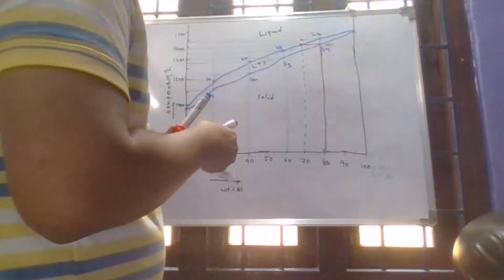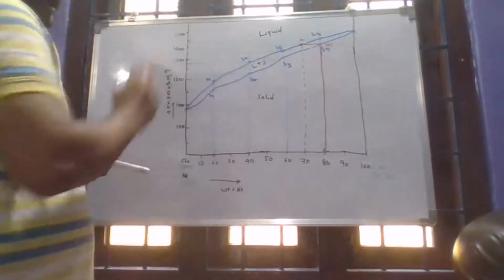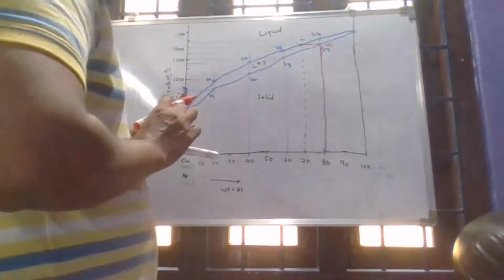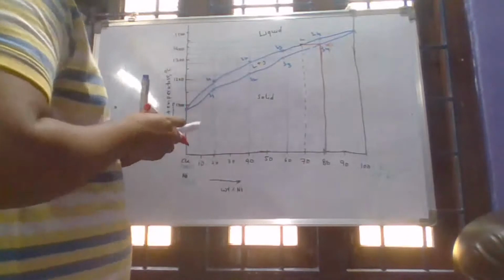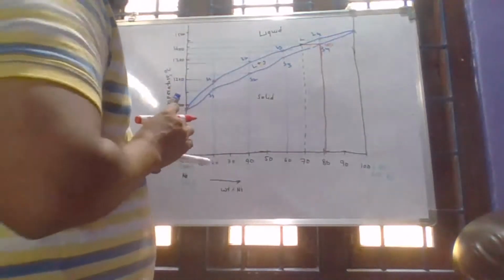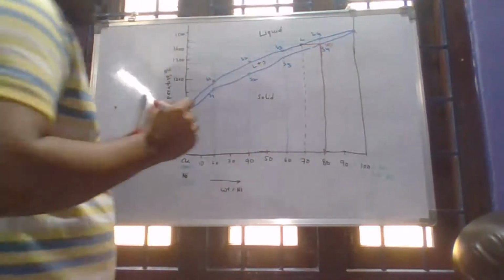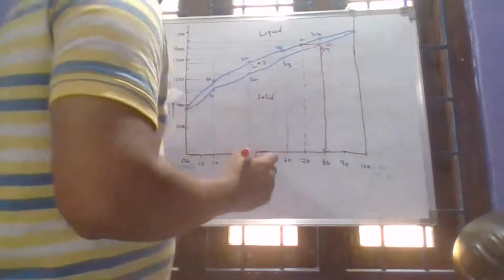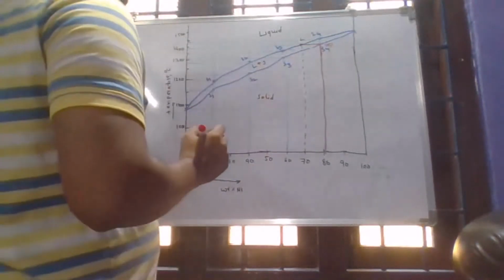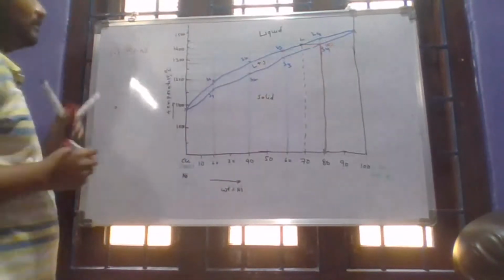So we can write the answer as: during solidification, which starts at point L and finishes at point S, the first solid which separates from the liquid has the composition given by the solidus line, 80% nickel. So the answer to what is the composition of the first solid is that the first solid freezing out from the liquid is at 80% nickel.